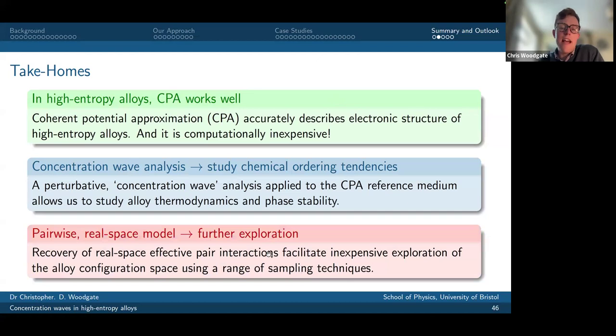And the third take-home message is the extraction of this pairwise real space model that lets us do further exploration of the alloy phase space. So I mentioned this idea that the Landau theory lets us get the initial ordering, but by recovering these effective pair interactions, we have this Ising-like model that we can then play with at all temperatures to really start constructing phase diagrams.